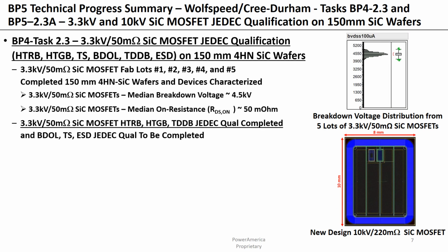Summing up, on BP4, the 3.3 kV, 50 milliohm silicon carbide MOSFET JEDEC qualification on 150 millimeter silicon carbide wafers: we've completed 5 fabrication lots and characterized the devices. The median breakdown voltage for these devices was 4.5 kV. Median on resistance is 50 milliohms. And to the right here, you can see the distribution of the breakdown voltage for these 3.3 kV silicon carbide MOSFETs.